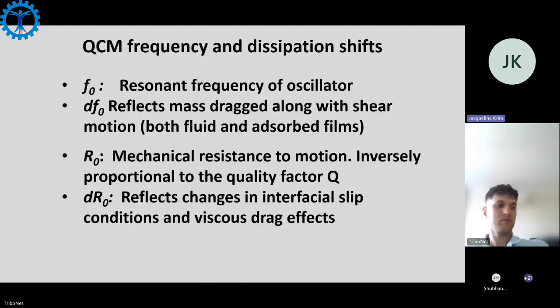What happens is the resonant frequency will change, and it was already dragging along some of the bulk liquid. So it might pick up some extra drag from particles, or if it's a very slippery interface, which we've only seen on occasion, it might decouple the whole thing from it and look like it loses mass. Meanwhile, the dissipation or the drag forces on the quartz microbalance, if you think of your hand swimming, the drag forces through water, they ought to increase if you're doing it through mustard or something. But sometimes when we add these particles, we see the drag forces go down.